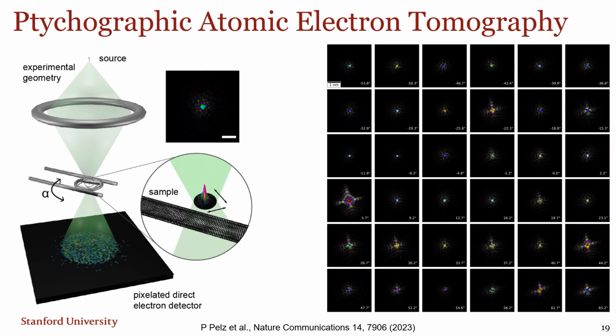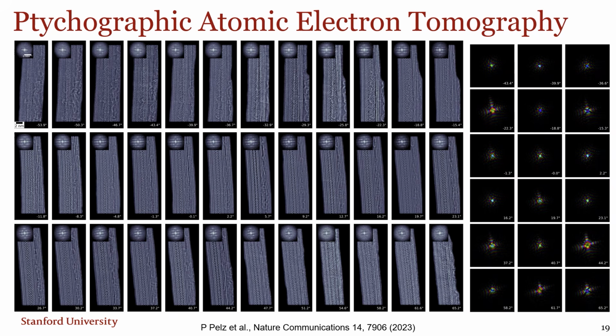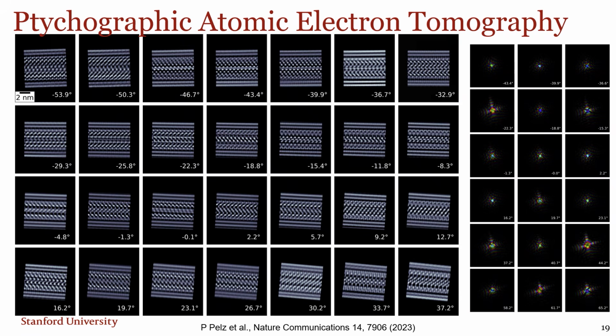So in order to solve the 3D structure, though, we have to do what I showed you before, solve the probe and solve the object, but over many different tilt projections of our sample. And so this is all of the different solved quantum mechanical electron probes. And these are the different quantum mechanical scattered waves of the nanotube nanowire at all the different tilt angles. So you can start to see the complexity of even a tiny structure like this.